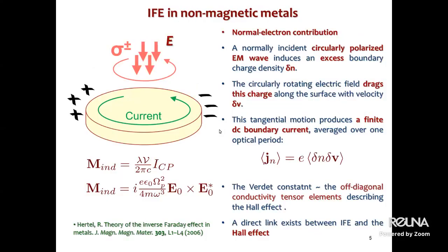The phenomenon of the inverse Faraday effect is a general feature of light-matter interaction. And basically, it should be observed across various media, including non-magnetic metallic systems and superconductors. The physics behind it is as follows. The instant electric field E of the circularly polarized light, incident normally to the metal surface, induces an excess of charge at the sample boundaries, which is dragged by the circular rotation of the field with velocity v along the boundary. The spatial rotation of the electric field leads to an in-plane motion of the charge density along the sample boundary, creating a non-zero time-averaged edge current and consequently giving rise to a DC magnetization or DC magnetic moment.